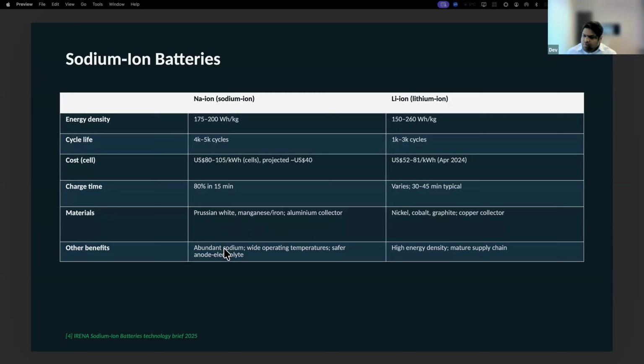The wide operating temperature. As you know, the lithium ion chemistry packs that are currently used in electric vehicles have to operate within a normalized temperature range. Too cold or too hot a temperature is not acceptable for current chemistries. That's why you have battery management systems or temperature management systems. However, the sodium ion chemistry can operate at much lower as well as much higher temperatures. So you don't need extra thermal management systems integrated into your car, which also lowers the cost of the car over a period of time. The anode chemistry or electrolyte is much safer compared to lithium ion.